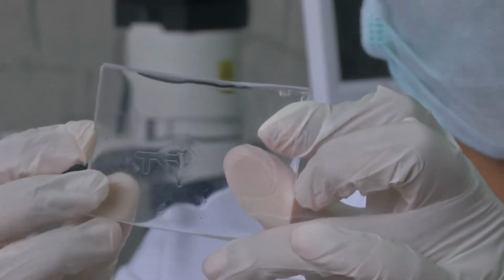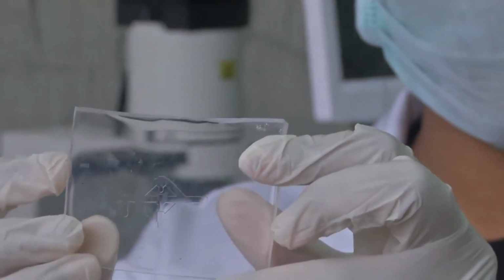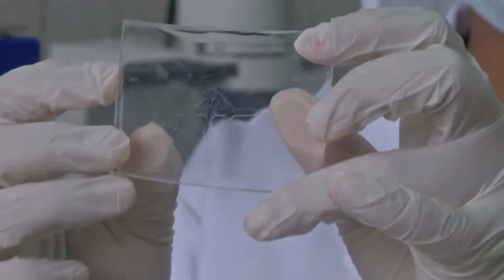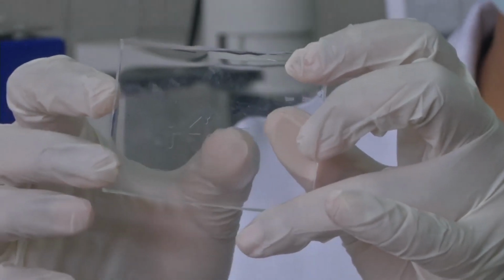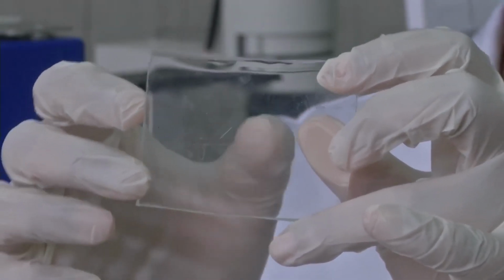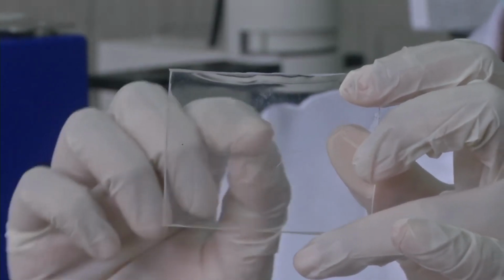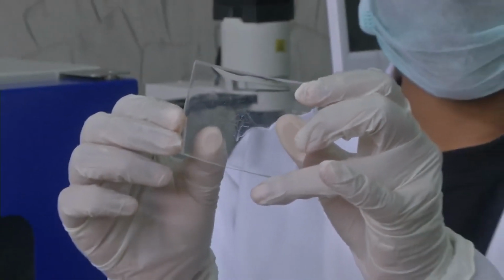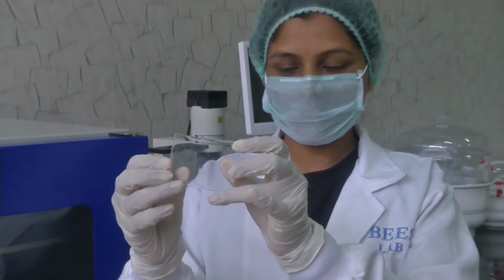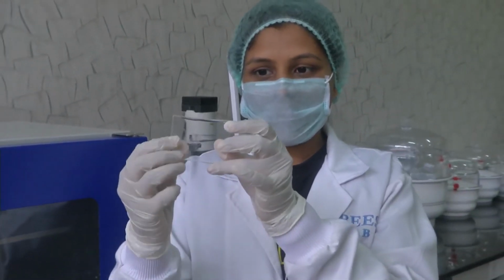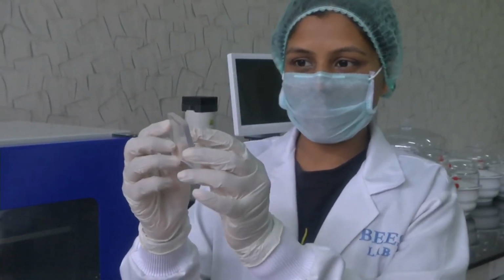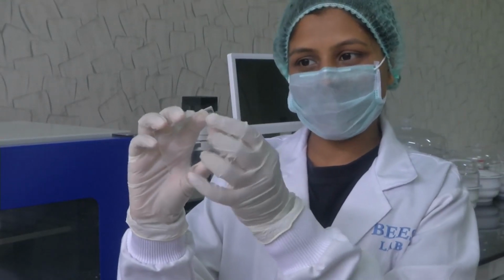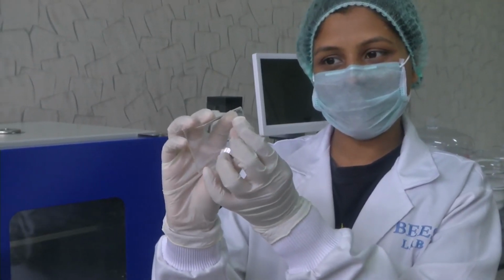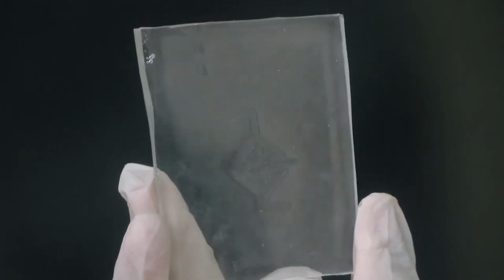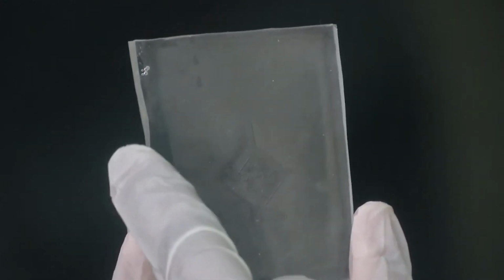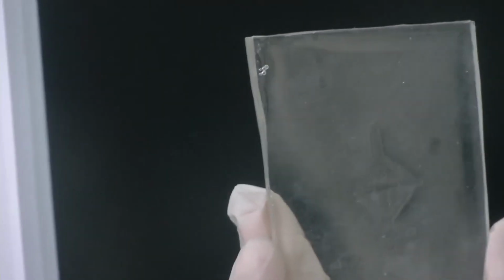Now, if you see this, you can observe how you can easily replicate the structure on your mold onto PDMS devices, and you could even mold channels of a few micrometers and nanometers in dimensions using this polymer. Another thing you can see here is there are tiny bubbles at the end. This is our device structure that we desired, but there are a few bubbles at the end.